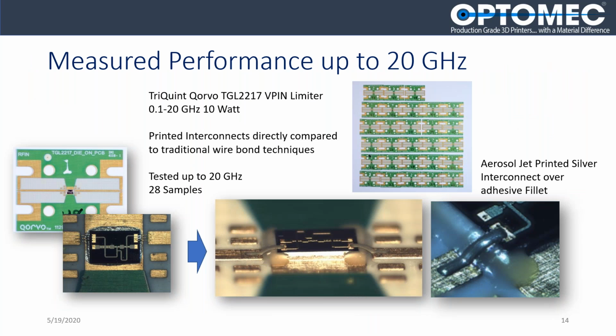So here is a physical manifestation of what I just showed you in the simulation data. Here we've got a TriQuint V-pin limiter with a 0.1 to 20 gigahertz range and 10 watts. And we printed about 28 of these samples and directly compared them to the equivalent wire bond structure that you see in the lower left-hand corner here. For the interconnect geometry, we essentially used a standard dispensing method to dispense a fillet around the bare die, and then printed the interconnect from the bond pad up onto it.